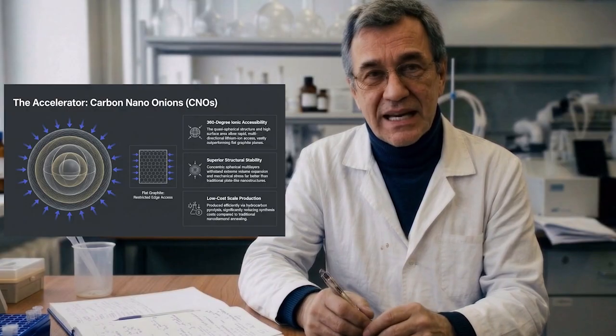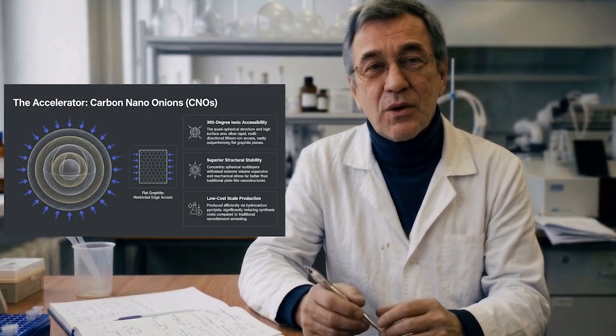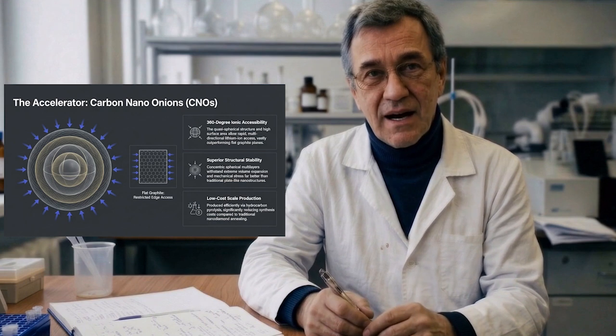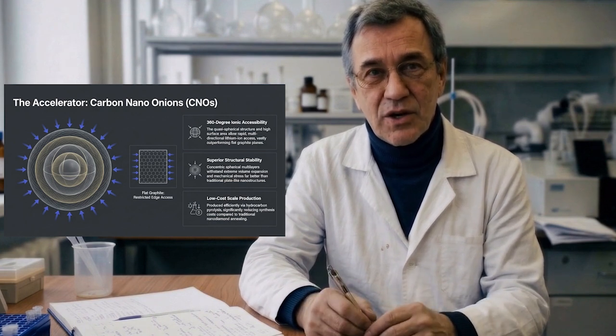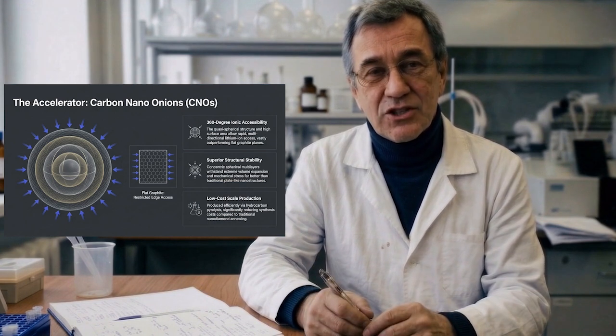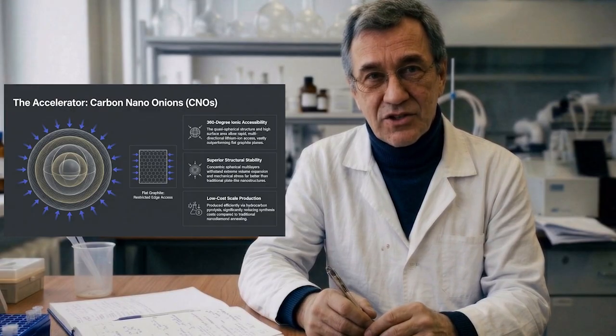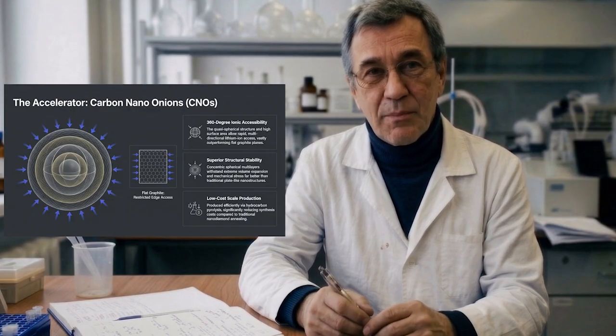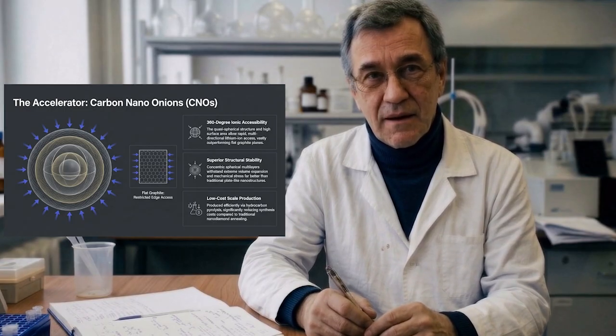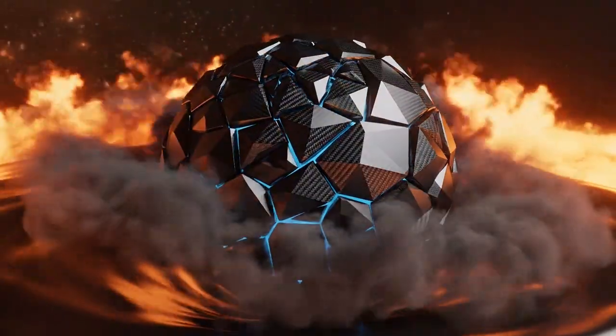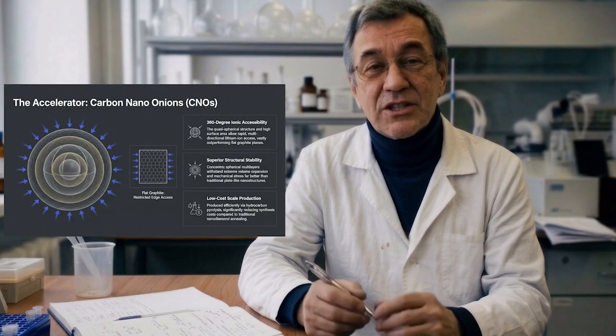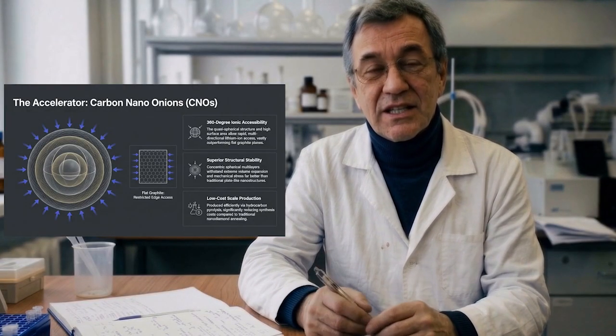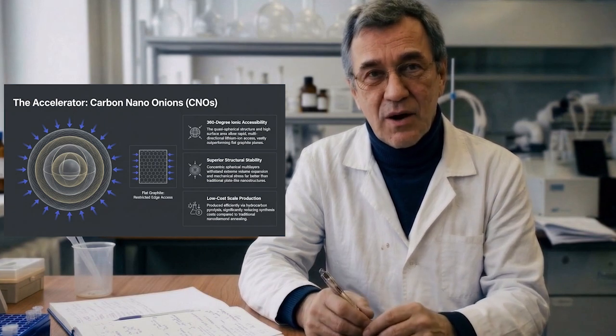CNOs offer unique advantages. Their spherical shape provides a large surface area for electrolyte contact, allowing lithium ions to access the material from any direction, which is great for fast charging. They are highly conductive, and their spherical nanostructure is inherently more stable than flat layers, allowing them to better withstand mechanical stress during lithiation. Our CNOs, produced via a scalable and cost-effective pyrolysis, show a high degree of graphitization with a near-perfect spherical morphology and a particle size of 30 to 60 nanometers. This process is significantly cheaper than methods using nanodiamonds.